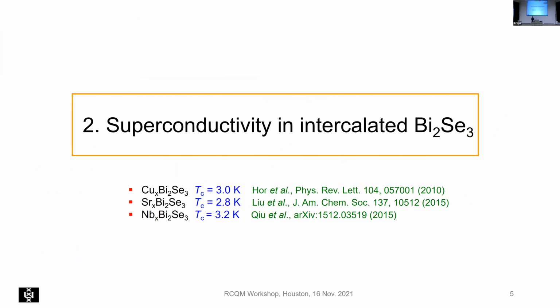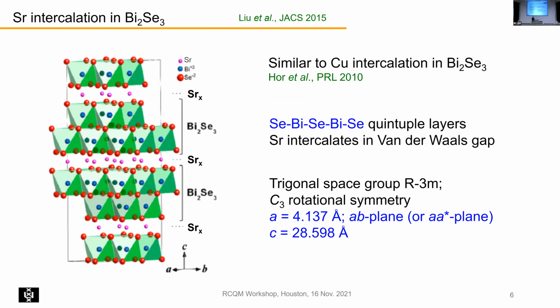Okay, let me then come to bismuth 2 selenium 3 intercalated. There are three of these materials, the copper, strontium, and niobium doped, and the Tcs are all in the order of 3 Kelvin. So let's first have a look at the crystal structure. We have these quintuple blocks of selenium, bismuth, selenium, bismuth, selenium. And these quintuple blocks are bonded together by van der Waals forces.